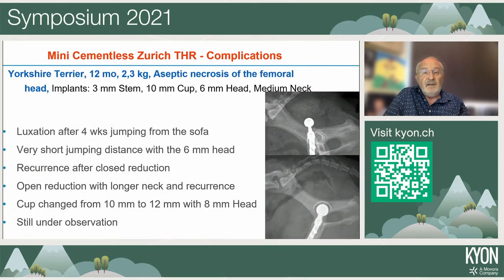The last complication, which is still under observation in my clinic, was a very small Yorkshire Terrier with a aseptic necrosis of the femoral head. I had to use a 3 millimeter stem and a 10 millimeter cup with a 6 millimeter head, the smallest size available. This dog was okay until 4 weeks later, when, jumping from the sofa, he luxated. Of course, with a 6 millimeter head, we have a very short jumping distance for the femur head to get out. After that luxation, it recurred after closed reduction. We did an open reduction again with a longer neck, but it recurred again. So we are quite desperate in this small dog.